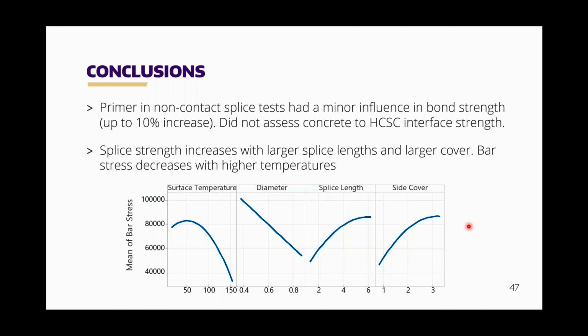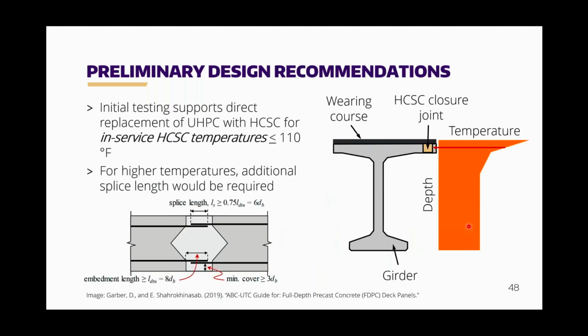Splice strength increases with the larger splice length and larger cover, just like it would for any other cementitious concrete. The new unique feature here is that bar stress decreases with higher temperature, which is a new consideration for design. So, preliminary design recommendations: this initial testing supports direct replacement of UHPC with HCSC for in-service HCSC temperatures less than about 110 degrees Fahrenheit. Maybe that's 120 degrees Fahrenheit. Certainly when we got all the way up to 145 Fahrenheit, then we saw a significant reduction.